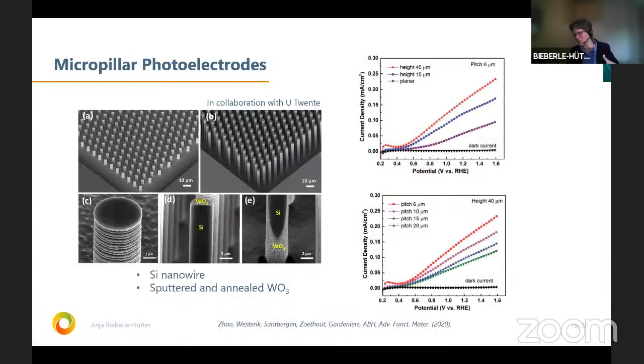So the next step was to go to the third dimension. So first from the glass substrate to a silicon substrate, and now from the silicon to micro pillar electrodes. And there we collaborated with the University of Twente together. So they were fabricating these nice silicon micro pillars for us, and then we deposited tungsten oxide by sputtering on top of it. And here with this cross section, you see that okay, sputtering is not a conformal deposition method, so therefore we have a thicker tungsten oxide on the top than on the edges.